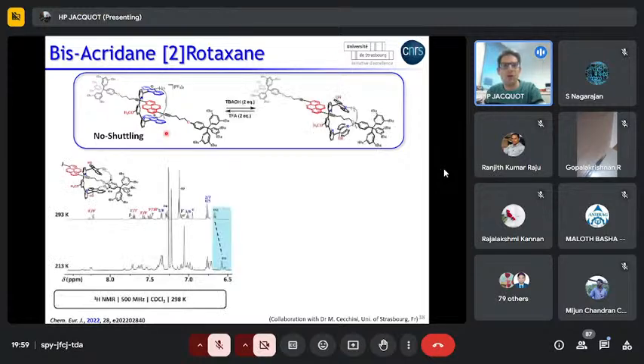Then we wanted to look at the bis-acridane derivative, so we added hydroxide ions. The proton NMR of this molecule shows that you have peaks from the pyrene recognition site which are closer to what they are for the free dumbbell. So this means that the macrocycle moves away from pyrene. Then also, you have only 2 sets of signals for this proton, which we call the MA proton, the proton of the stopper.